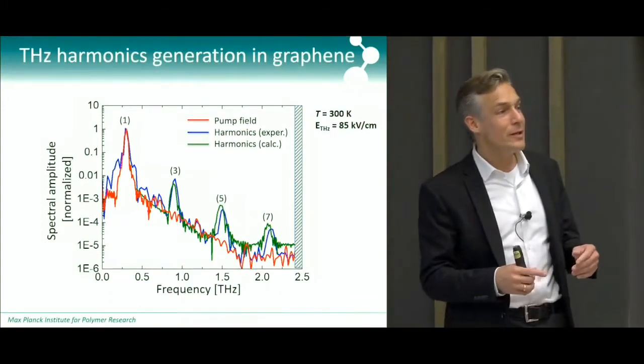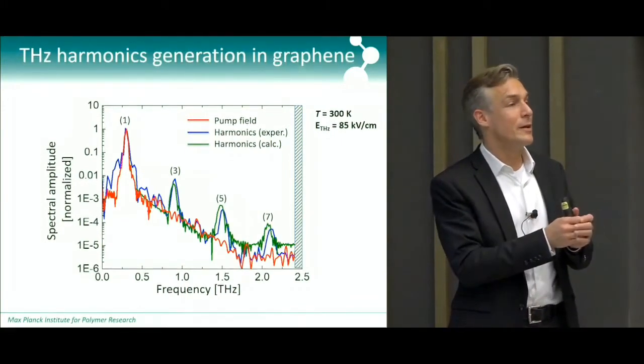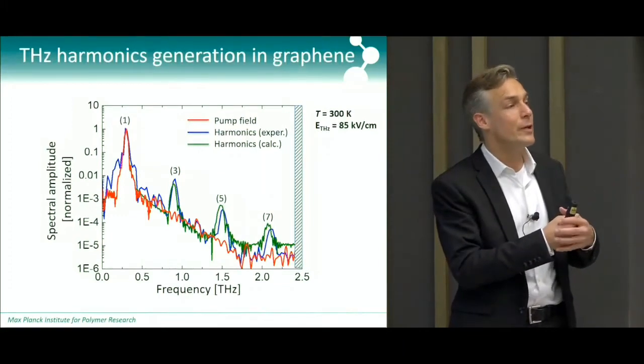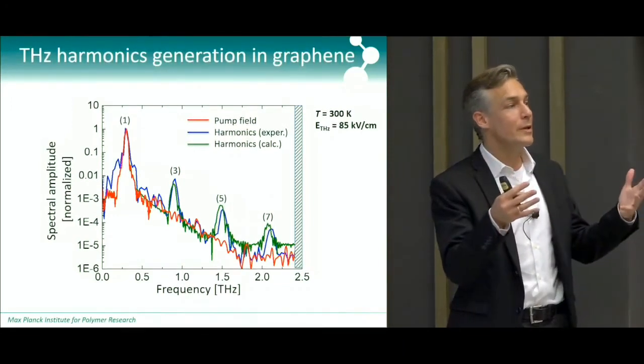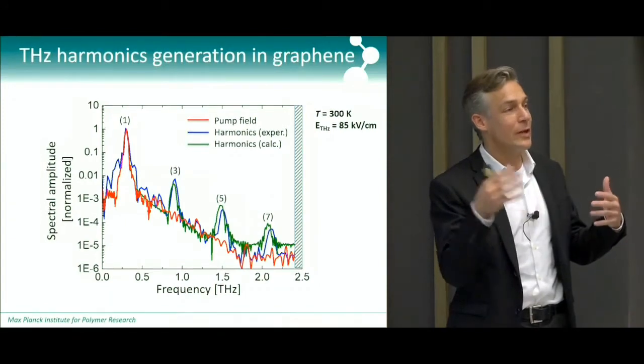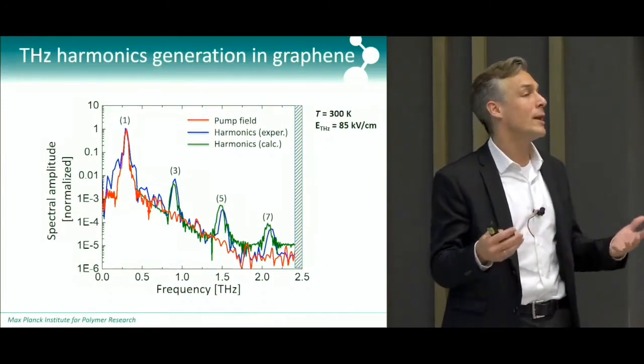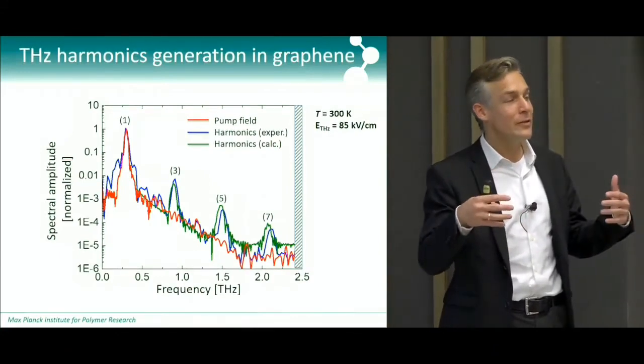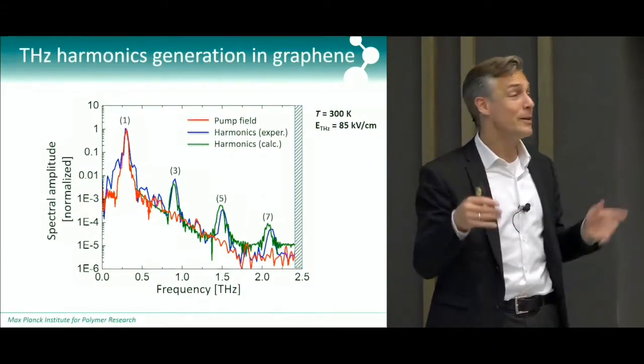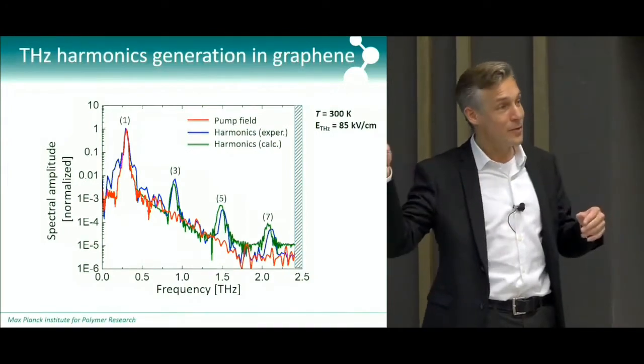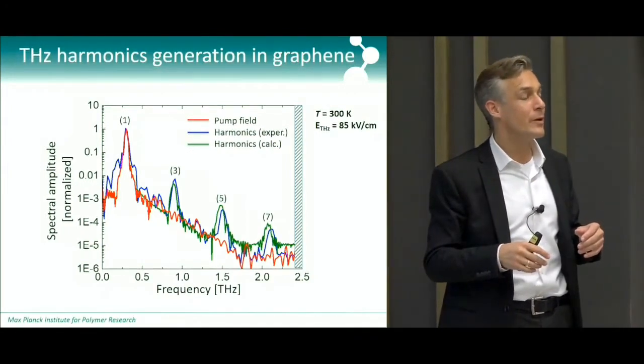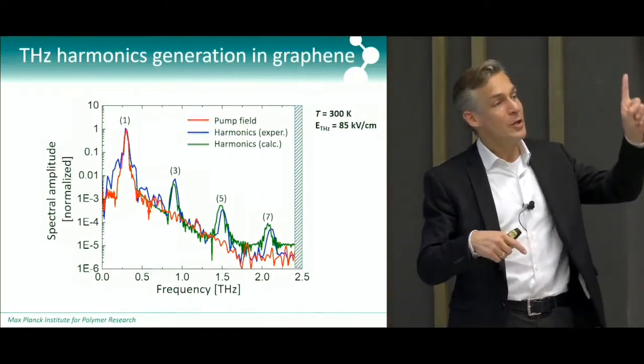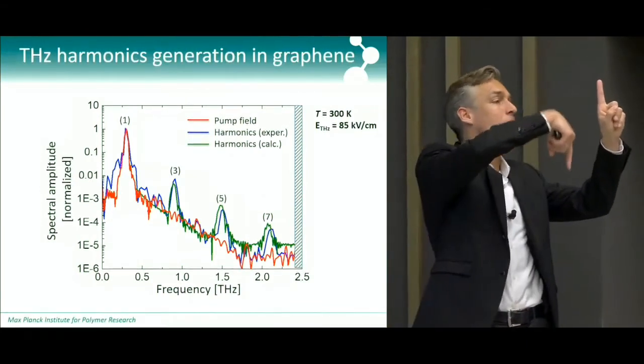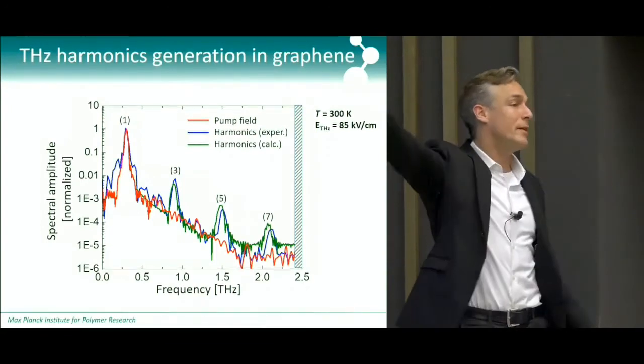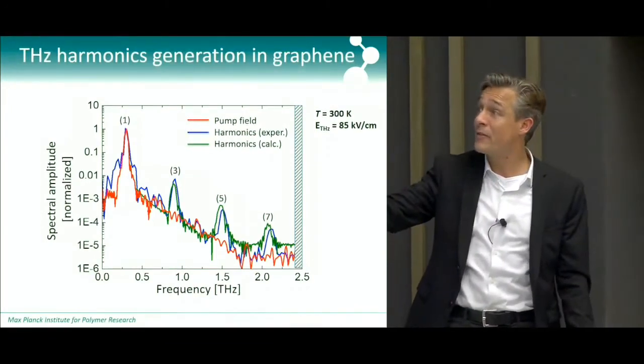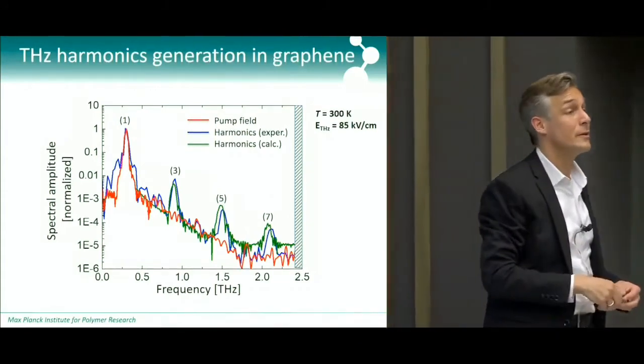That is the symmetry. This is centrosymmetric. Graphene is a centrosymmetric material, and so the second harmonic and fourth harmonic signals are not dipole allowed. So you will generate locally very high second and higher even order polarizations, but for each polarization that you create in one direction, there will be another that cancels it out. And so the net in the far field, you see really nothing. I mean, there's really nothing there.